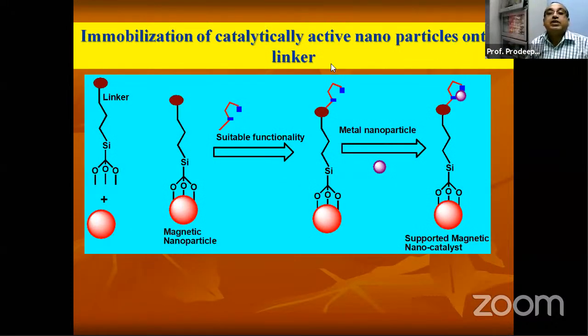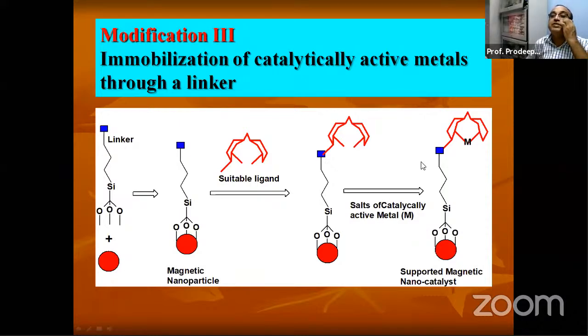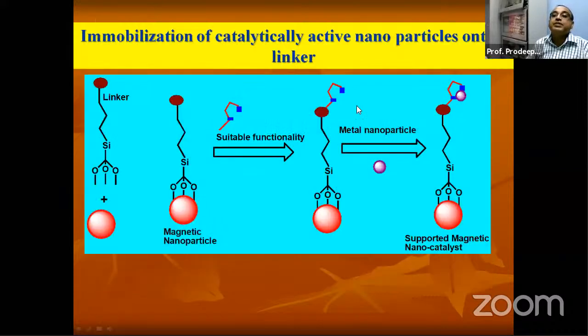Then another is the immobilization of catalytically active nanoparticles onto the linker. So this is the linker again, magnetic nanoparticle, and here a suitable functionality, you add it, then get this nanoparticle. So what is the difference between this and this? Here, you take these salts, then make a metal complex on the surface of the magnetic nanoparticle. And here, you make a linker, use some metal nanoparticle, and hook it on the surface of the magnetic nanosupport.